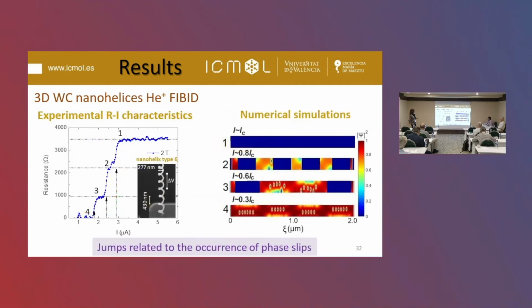Interestingly, we observe a completely different behavior in one type of nanohelix. Here we observe how the resistance as a function of the current shows different jumps, which are related to the occurrence of phase slips, as supported by numerical simulations based on the time-dependent Ginzburg-Landau equation, in collaboration with Professor Fomin as well. Here we can see at point number 4, for example, the vortex patterns inside the nanowire, and at some moment, when you increase the current, two large regions of phase slips are introduced into the patterns, producing that large jump in the value of the resistance.